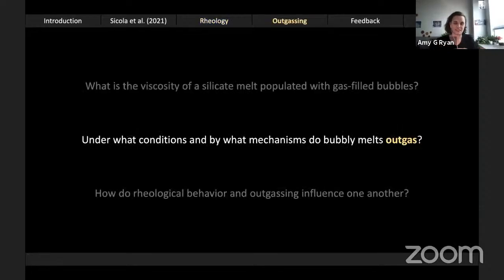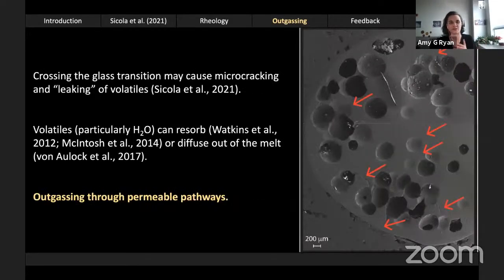The outgassing story is much more succinct, but I think equally as cool. The objective here is to figure out how and when bubbly melts outgas. I've already introduced a couple of ways in which a bubbly melt could lose its volatile phase. One would be microcracking upon crossing the glass transition, leading to a leakage or drainage of volatiles. Another would be the resorption, particularly of volatiles like water, and their diffusion out of the melt. That's another way to bleed the system of its volatiles. What I'm going to focus on, though, is a much more physical process, and that's outgassing following the creation of permeable pathways.